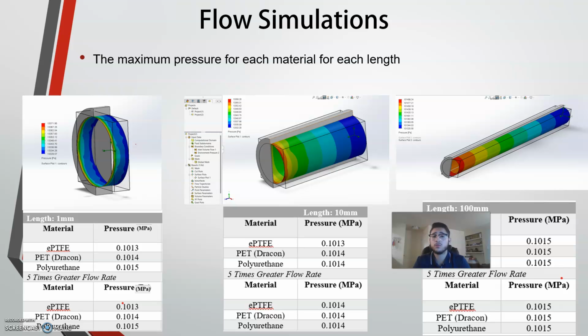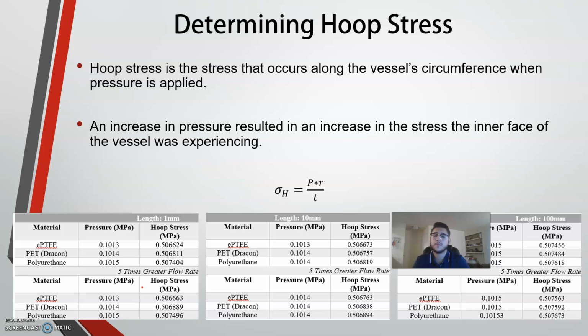The results showed that the material had little to no effect on the pressure experienced inside the vessel. The 1 millimeter showed results in the 0.1013 megapascal range, the 10 millimeter showed results in the 0.1014 megapascals, and the 100 millimeter showed results in the 0.1015 megapascals. They're actually relatively close to each other. There is not much difference.